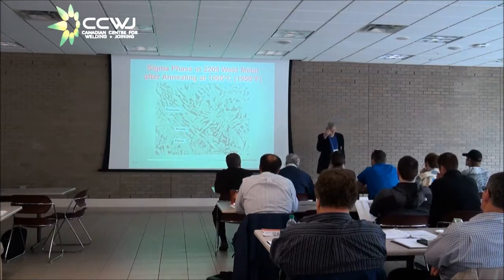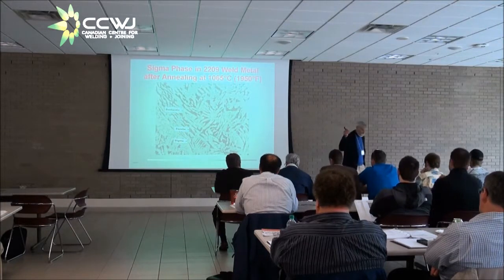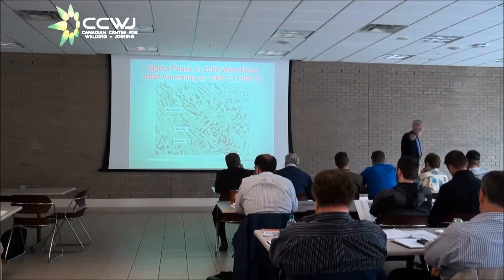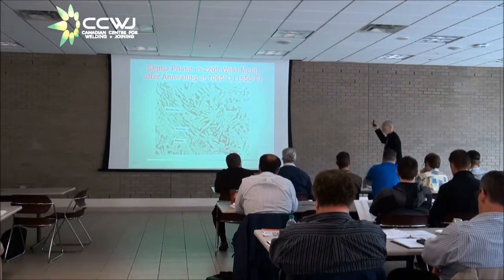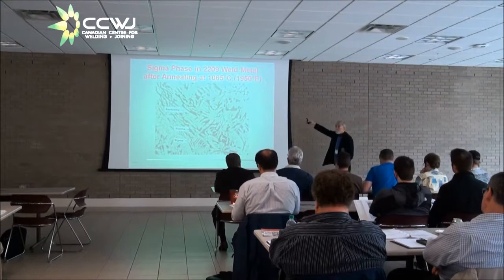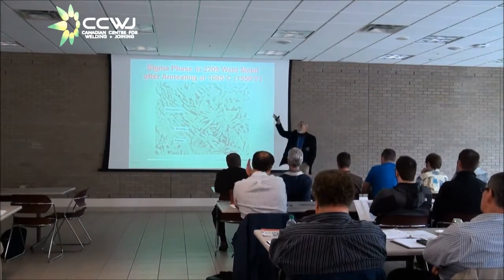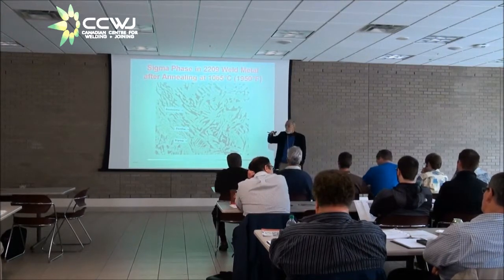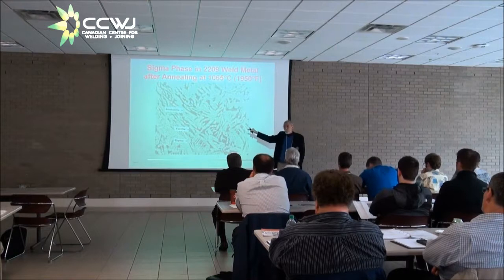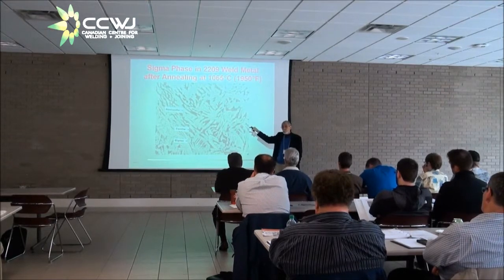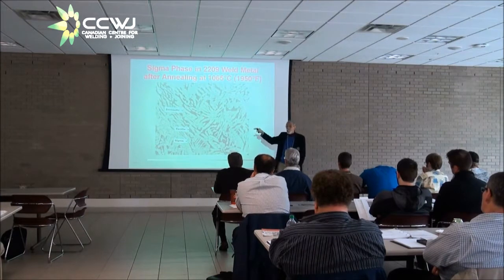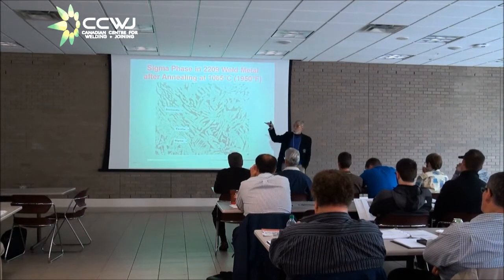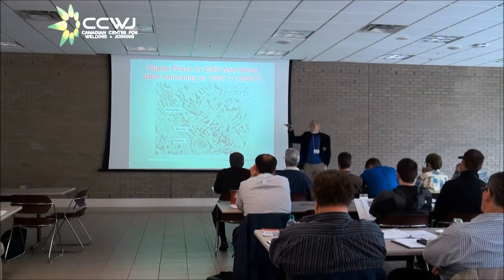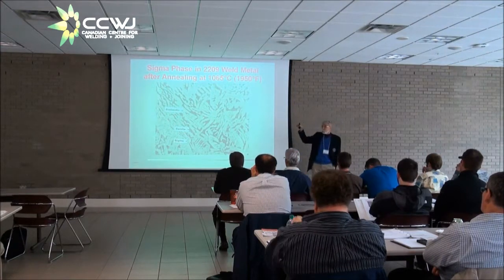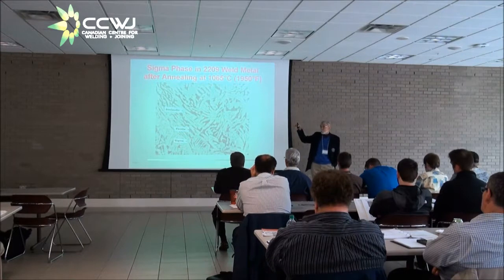Now that was kind of interesting to me, because when you start out with high ferrite welding, let's say you get a 60 or 70 ferrite number in the as-welded condition and you anneal it, you will see the ferrite number drops appreciably. But if you start out with a ferrite number around 45, it doesn't drop. And the reason is because the alloy started to form austenite at higher temperature, and you got very close to equilibrium partitioning, very close to the equilibrium amount of austenite.